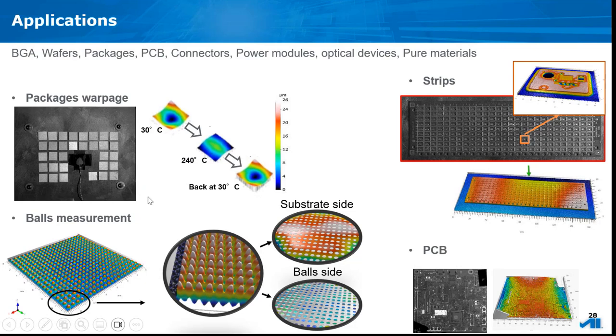We can also measure a larger sample, such as a strip, and get the full strip shape or one single unit shape by just changing the length extension. During the same profile, we can get both information. We can measure more complex samples, such as BGA with ball, for instance, and we can capture the ball and the substrate all together. Then our software is able to mask the ball area to get only the substrate warpage, or mask the substrate to get the ball warpage. We can have PCB, we can have wafers, and different other samples.